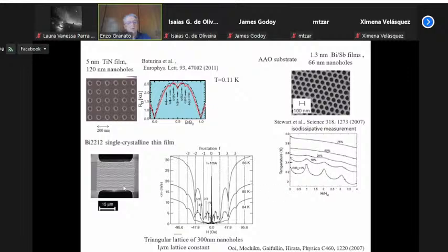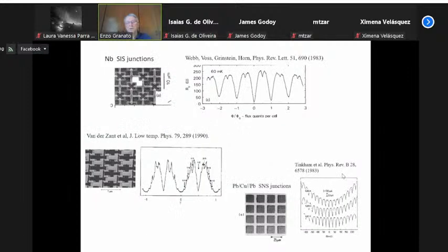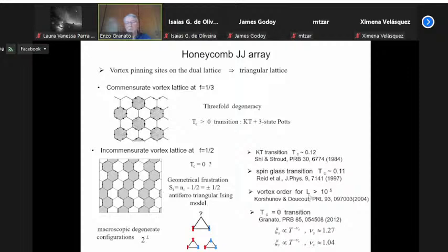This is another system which also has a triangular array of holes, with a 300 nanometer spacing of nanoholes, though you cannot see it in the figure. This is a high-Tc superconductor, measured as a function of the magnetic field. Here they didn't parameterize in terms of frustration, but you can. There are minima at the integer values of frustration, but if you look carefully, there's no minimum at frustration 1/2, because this is a triangular array. This is consistent with what we mentioned before, that for the honeycomb array it appears that there is no transition at finite temperature.